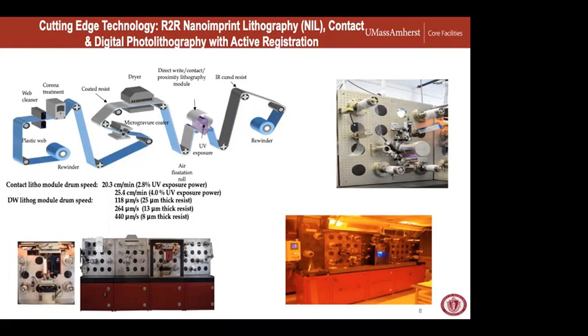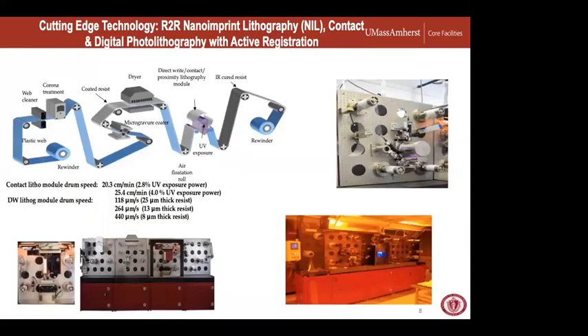If you look at the image on the right, it shows our drum. In the center of that, you can see a little bit of a purple color where the UV source is coming out. Also, the picture below that shows the blue image. If you look at that top right picture, you also see there are 2 cameras that will image the alignment capability. What that does is allow us to adjust in an XY translation the position of the substrate with respect to the photomask, so you can hone in on the alignment between the existing pattern and what you're trying to pattern. We've been doing a little bit of work with that, but haven't fully vetted it out. Again, we're targeting something that is less than 20 microns, possibly down to less than 5 microns in alignment resolution and accuracy.